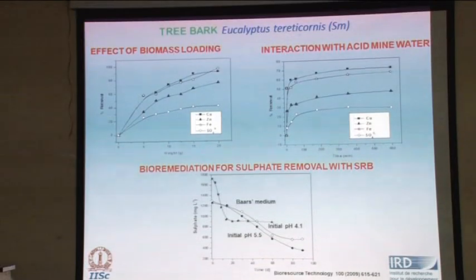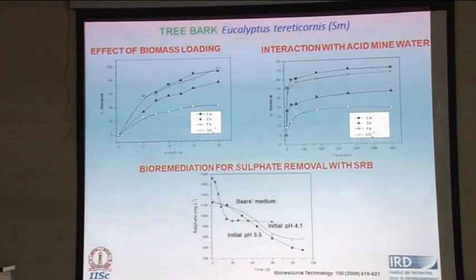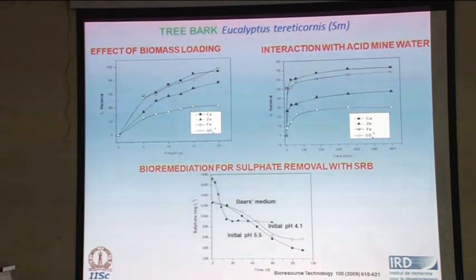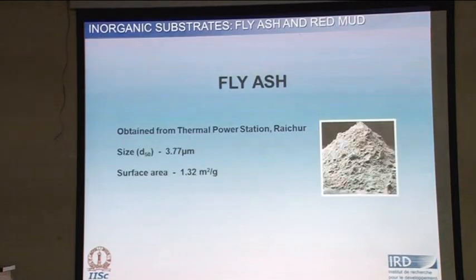So we also did some work with respect to the tree bark. Again, you find a similar trend, that you have complete reduction of iron. You have copper and zinc also getting reduced to a great extent. The sulfate reduction is actually better compared to the control medium when we use the extract from the tree bark. Another important thing is with respect to the pH. Again, you will find that you are able to increase the pH in the presence of these reagents.